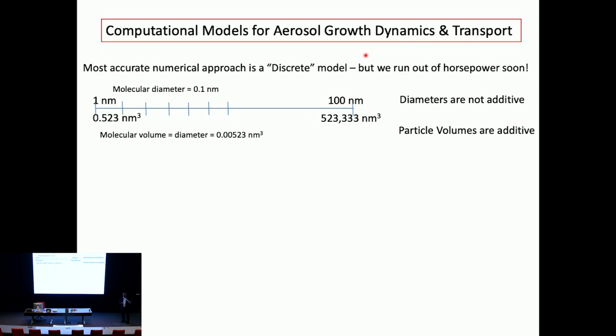Let's say I want to solve in the range from 1 nanometer to 100 nanometer, rather small range. These particles could be in a whole spectrum of sizes. I will write down the volume below, and just assuming it to be spherical, use the relationship. So you see that it goes from 0.5 nanometer cube to about 500,000 nanometer cube. But I want to know the concentration at every particle size. The increment in the particle size is basically one molecular dimension, right? Because one molecule could add up to my smaller particle and become slightly larger, and so forth and so forth. So I keep track of the molecular volume, which is shown here, and just approximate numbers and assuming things to be spherical. And the reason we like volumes is also when two particles collide, I can just add up their volumes, so that volumes are additive, whereas diameters clearly are not, and there's no concern about the shape and things.